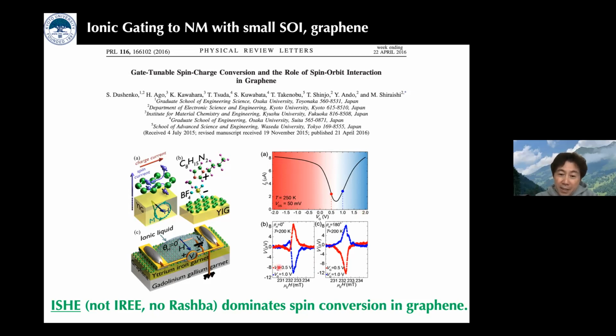Thanks to this change of polarity, we can see the polarity change of the inverse spin Hall voltages by applying the gate voltages. More importantly, we can apply a very strong electric field to the system, so we can clarify the spin conversion physics behind this ambipolar spin conversion. We clarified that the inverse spin Hall effect, not the inverse Rashba-Edelstein effect, dominates the spin conversion in single-layer graphene, even though spatial inversion symmetry is broken along the direction perpendicular to the plane.